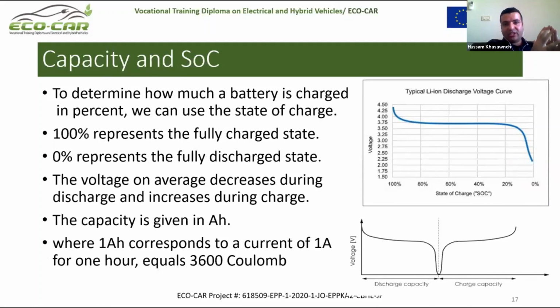To better understand, let's look at the voltage when a lithium-ion battery is discharged. In this figure, the y-axis is the voltage, the positive-negative electrode voltage difference, and the x-axis is the state of charge. We start with a fully charged battery, and then go this way to fully discharged. So it's a discharge voltage curve. As we can see, the voltage generally decreases during discharge. This is because the lithium ions that have the largest chemical driving force will go first from the negative to the positive electrode. That's why the voltage starts dropping.